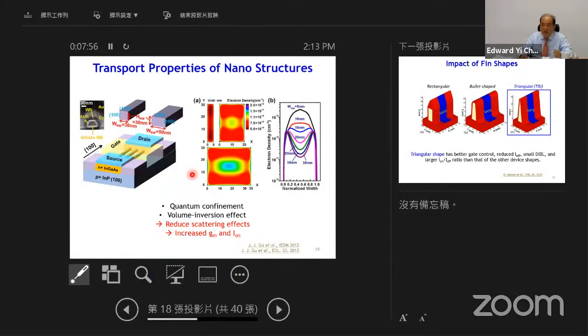Okay, and other than the interface at the high-K material, you can further improve the quality of the MOSFET by reducing the InGaAs fin thickness. If you reduce the fin dimension, you can see there's so-called quantum confinement. All the electrons are confined to the center, and the number of electrons is increased, and also because they are not on the border side, the scattering is reduced. So overall, the electron density increased due to the reduction in dimension, due to the quantum effect. And electrons also have less scattering, and that gives you a higher current.